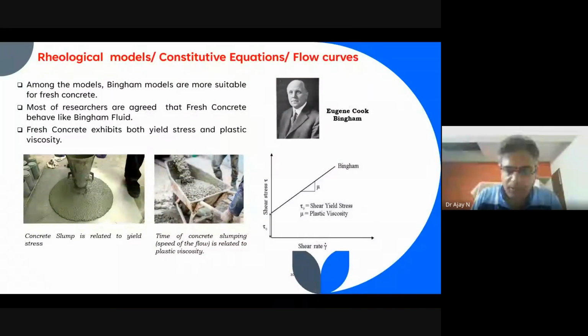Yeah, we are into the theoretical model. So from rheometers, we get the values for shear stress and shear rate, and fit them with the Bingham equation. The Bingham equation suits concrete, meaning that any concrete has some initial force. That force we call the yield stress, because between aggregate and aggregate we have friction force. For example, take any SCC mix: when we fill up the slump cone and start lifting it, the minimum force required is what we call the yield stress.